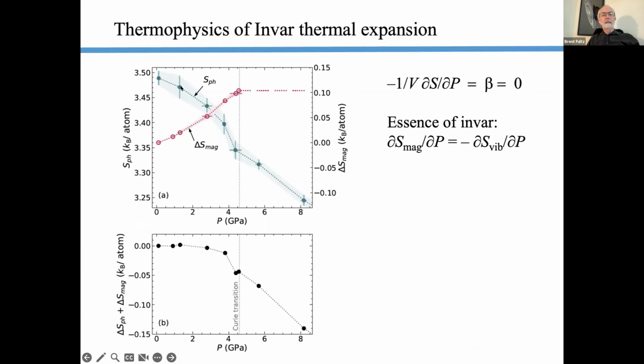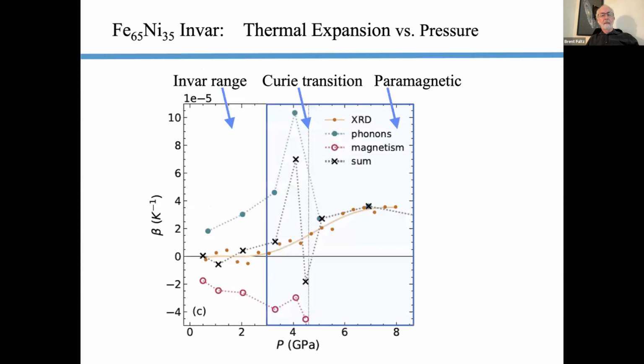Here's the phonon entropy. It's decreasing with pressure, and the magnetic entropy is increasing, and they cancel each other out really quite well. The electronic contributions, which were also from the theory, didn't change nearly so much with pressure. So this is the essence of INVAR. It's a very delicate balance between the phonon entropy and the magnetic entropy, their pressure dependencies specifically, and it's aided by the spin-phonon coupling. By the way, we can individually plot out what the thermal expansion coefficients are from the phonons and from the magnetism.